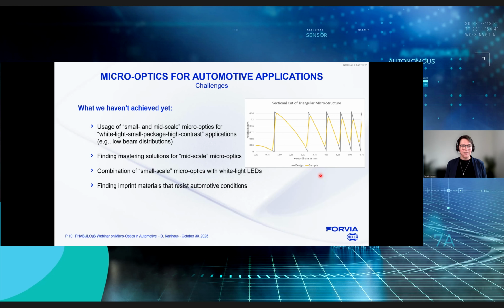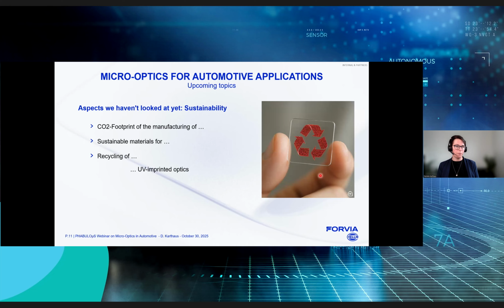And the final point is the imprinting material, especially when we look at nano imprinting or UV imprinting in general. We have not found a material yet that resists our automotive conditions. So when we bring, let's say, a glass element with a UV resist on it into our material tests, for example, a thermal shock test from -40 degrees to 120 degrees, then we see delamination effects or cracking or something like that. And therefore, we still look for a solution for that.